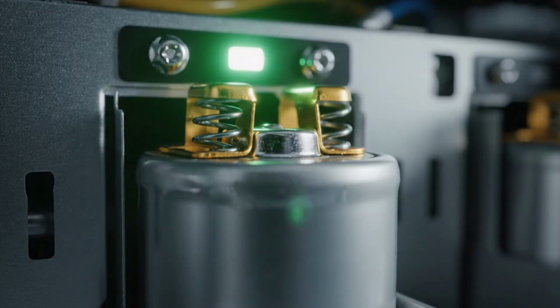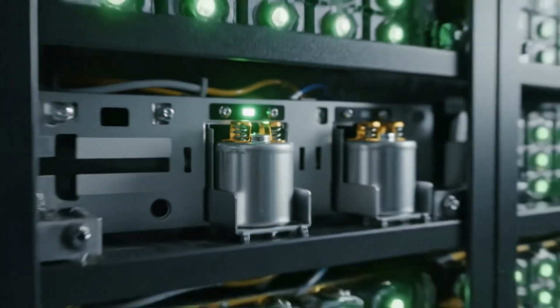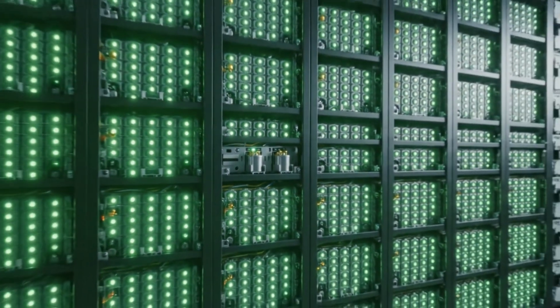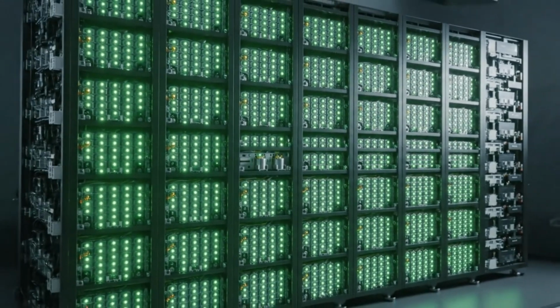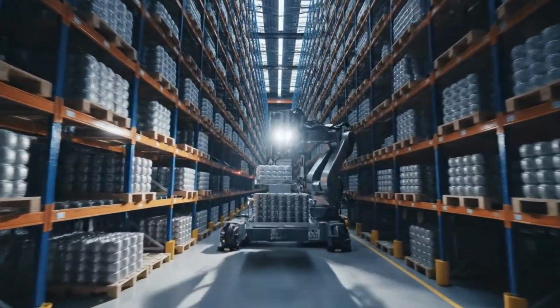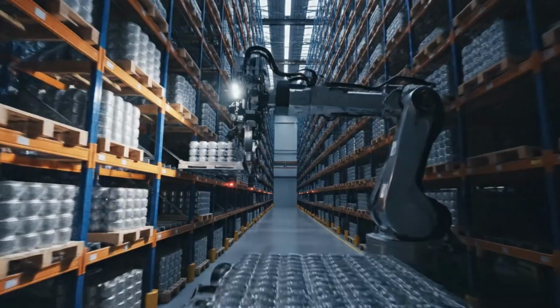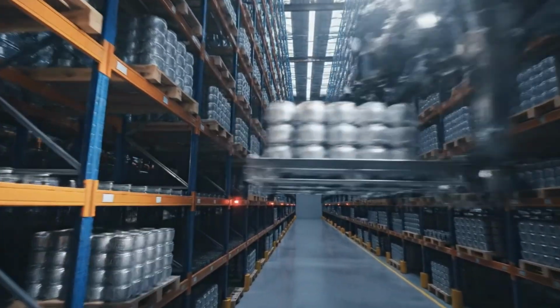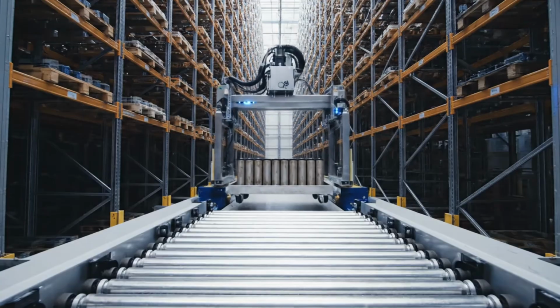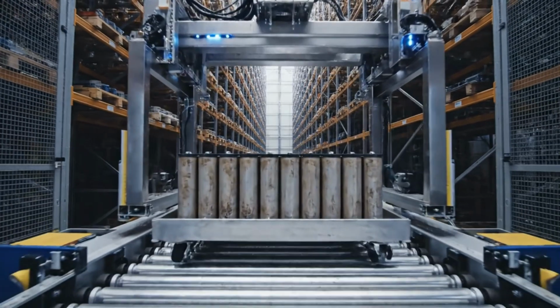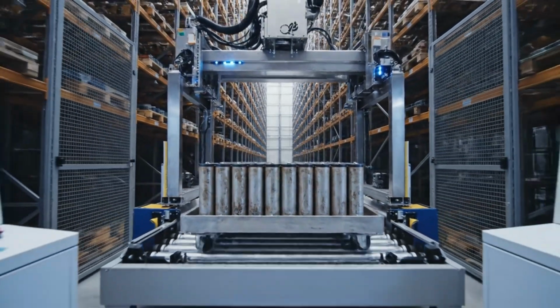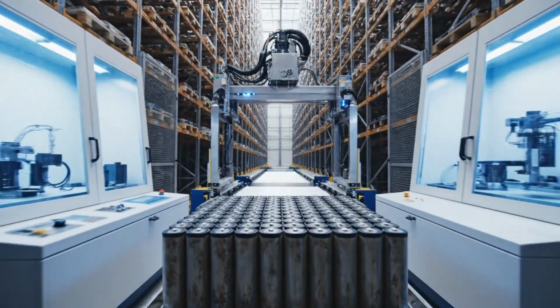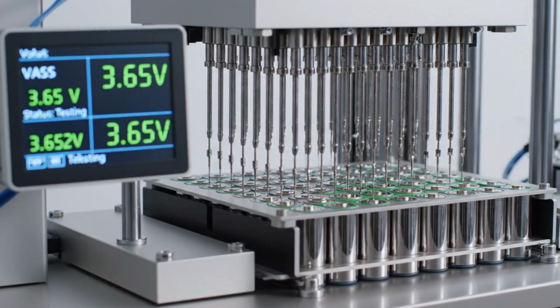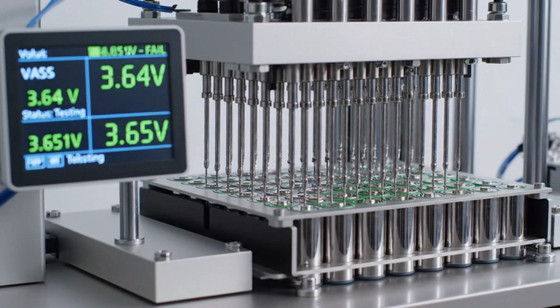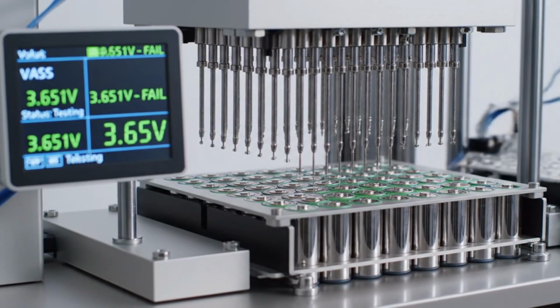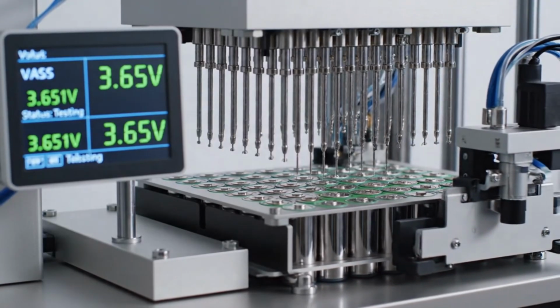This first charge, known as formation, awakens the battery, creating a protective layer on the internal electrodes. The cells are then stored in a temperature-controlled warehouse for weeks, aging to ensure the voltage remains perfectly stable. After weeks of aging, the cells are retrieved to verify they have held their charge without self-discharging. The OCV tester measures voltage to the third decimal place, rejecting any cell that shows even a hint of instability.